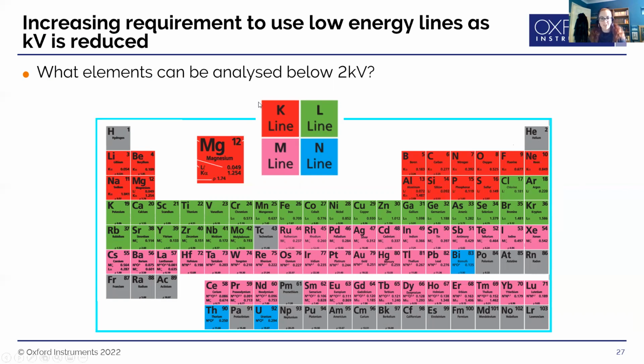So it becomes quite challenging when you're dropping down your kV, and it means we can't often use the K lines. The K lines are great because they're really obvious and you get lots of information out of them, but you may have to use one of the lighter or lower energy lines, and you can see here on this periodic table where we've highlighted which of the energy lines you need to use and which you can below 2 kV in this example.